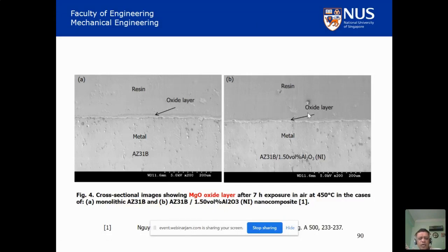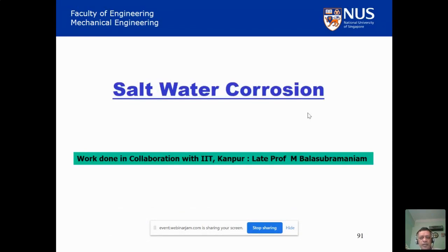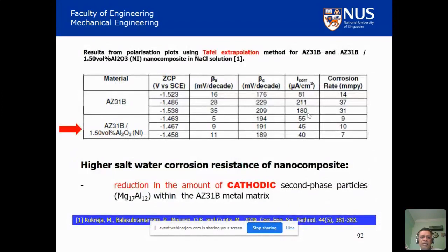It is similar to the observation made by many researchers, for example, in Australia, where they say that refining the grain size of steels improves the corrosion resistance of the steel. So here also we are doing the refinement of the grain size, and by that the diffusion of the ions to heal the layer is much faster, and that's why the dry corrosion resistance increases as a result of the presence of nano reinforcement. We also sent some samples to late Professor Balasubramaniam at IIT Kanpur, who investigated the wet corrosion, and he realized that the wet corrosion of nanocomposite samples based on AZ31 commercial magnesium alloy was almost 1/3 that of the base metal.